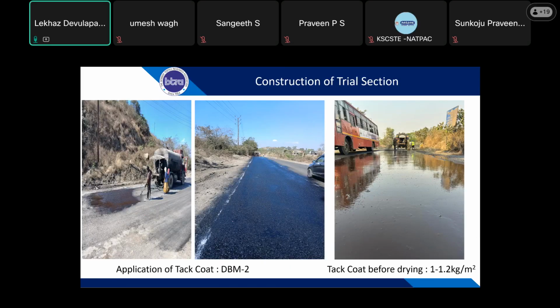This is the application of tack coat. Here I want to stress one thing: the tack coat application for the polyester geogrid was 0.4 to 0.5, whereas in case of the grid which has two non-woven backing, we went up to 1 to 1.2 kg per meter square. This is other research which we did with the industry for their specific geogrid. The 0.4 dosage is not giving a good bonding between the grid and the bottom layer and the top layer, so we have increased the dosage to 1 to 1.2 here.